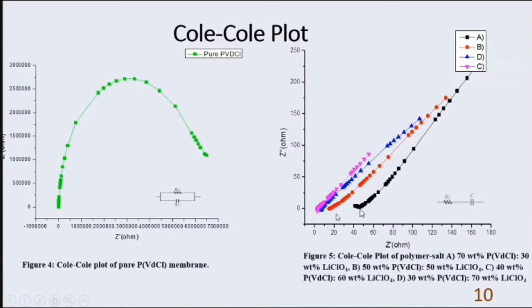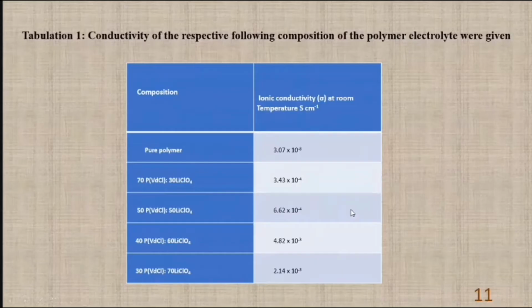So when resistance increases, it is taken from the x-axis. The resistance is used to calculate the ionic conductivity. Here the pure polymer is of the order 10 power minus 8, which is merely an insulative nature. As the salt is increased, the ionic conductivity of the membrane also increased. The highest conductivity is found to be of the order 4.8 into 10 to the power minus 3.